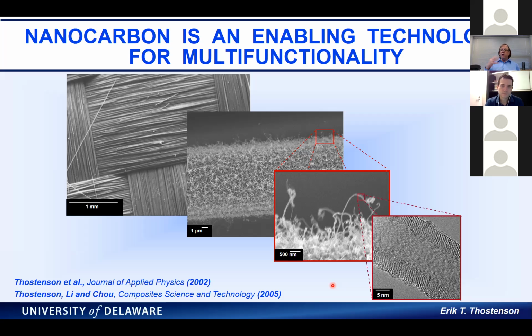But we can also modify the electrical properties, and that's where I think this aspect of multifunctionality has really grown. With carbon nanotubes, you have these high aspect ratios. So even if you just mix in a small amount, less than 0.1 weight percent, you can take pretty much any polymer and make it maybe not a real good conductor, but make it conducting. And then it also adds this sensing functionality.